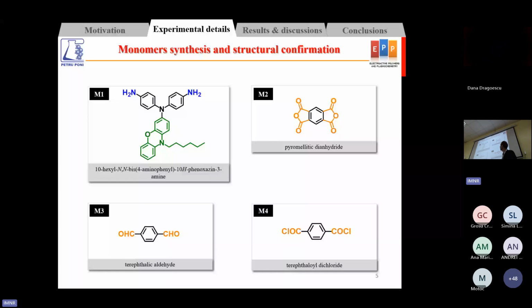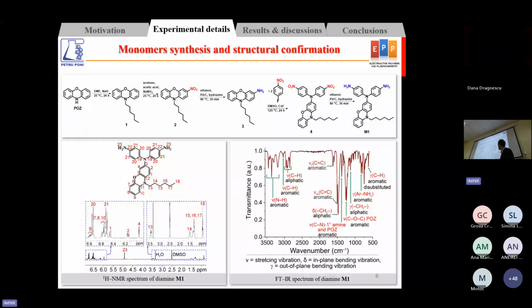The diamine incorporates some important structural elements to improve the electrochemical stability. The structure is in a propeller model with a double electron donor core and aliphatic chain to enhance the solubility of the polymers. The diamine was synthesized according to this scheme, and the structure was confirmed by NMR and IR spectroscopy. For example, in the NMR spectrum, the diamine showed the corresponding signal of the amine functional group.